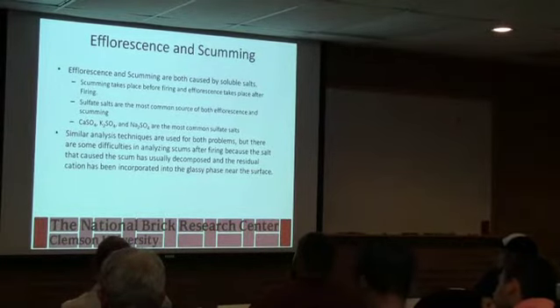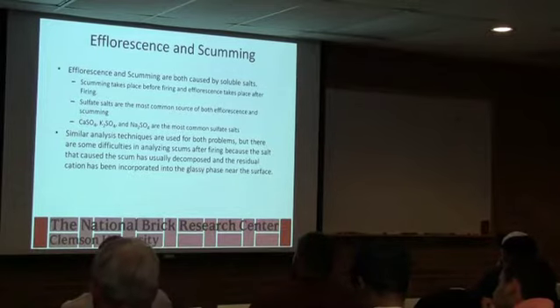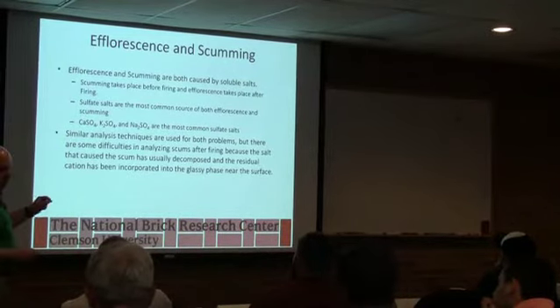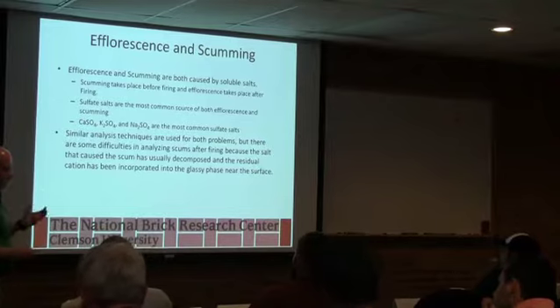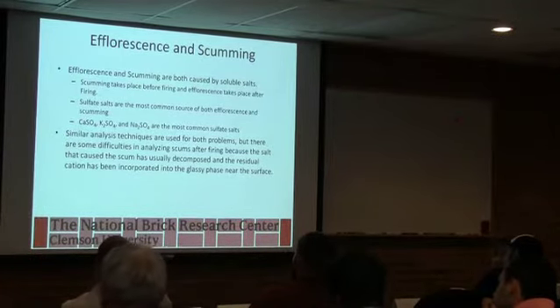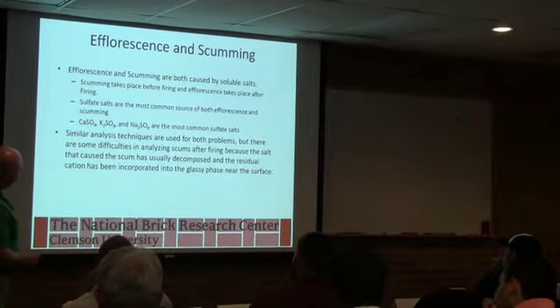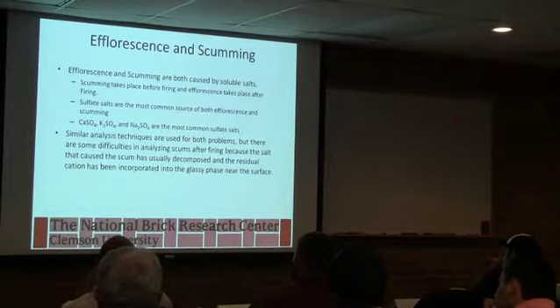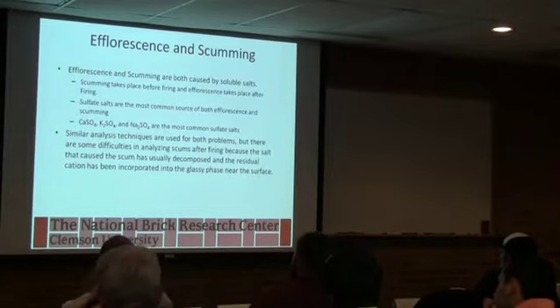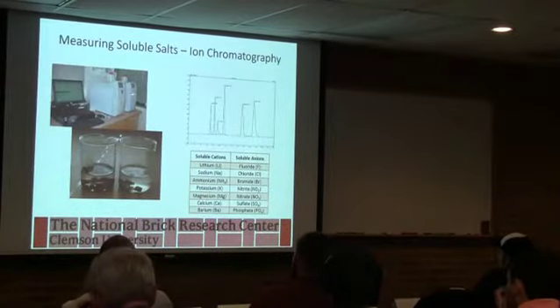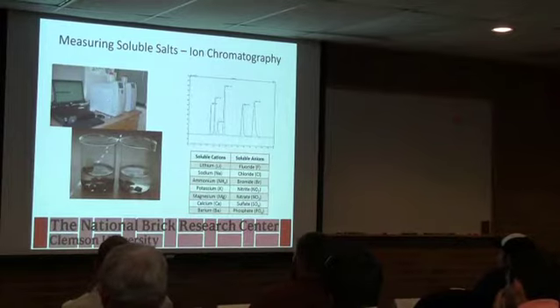Bad thing about scumming is, though, after you fire it, that becomes a permanent surface feature. It's incorporated into the surface, and scum doesn't come off after it's fired. It's generally permanent at that point. Efflorescence, you can have some luck with cleaning, depending on what it is. But we still do a lot of work on scumming and efflorescence. These are the ion chromatographs. Like I said, we can measure different salts.